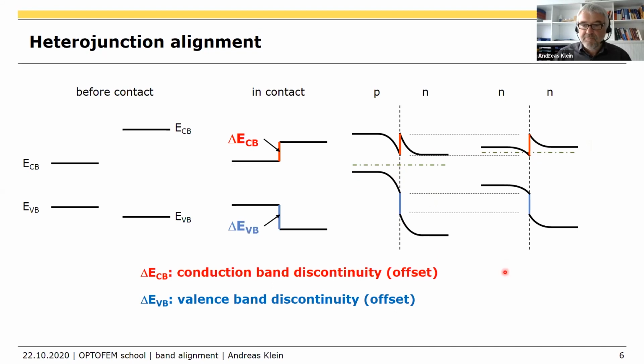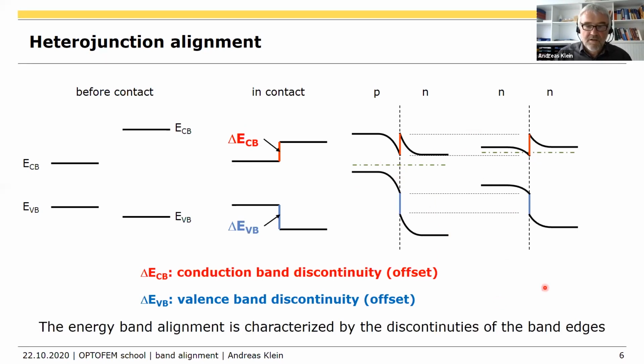And as for the Schottky barriers, these discontinuities are always the same. So they should not depend on the doping of the semiconductors. The discontinuities are the important quantities. Okay, so now how do we determine that? We do that by XPS, X-ray photoelectron spectroscopy.